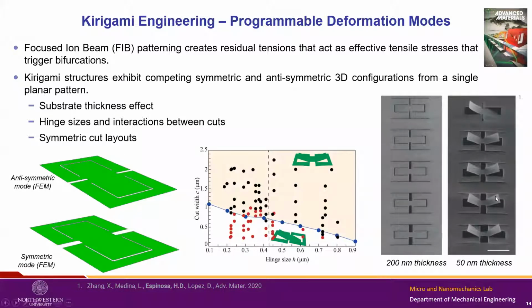And this is basically what we observed. So, an interesting substrate thickness effect. Once we go beyond a certain threshold, the Kirigami effect does not appear, but below a certain threshold, these Kirigami motifs appear. And what we saw in our, I would say, more limited investigations was that we can obtain two kinds of patterns: we get antisymmetric modes or symmetric modes. But there are some interesting complex 3D shapes which can be used.